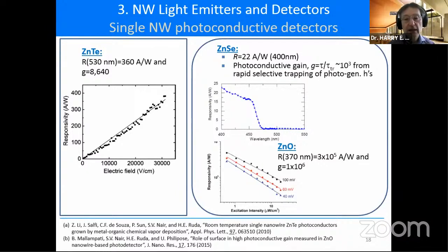So here's a bunch of examples for you of work we've done on making photodetectors, photoconductive detectors, and what you can see is, unlike normal traditional detectors where we're talking about amps per watt as a normal number, if we look, for example, at the zinc oxide one at the bottom there, you can see that we can have numbers like millions of amps per watt from or close from these wires, and that's because the gain is very high. And what's happening, and we're going to come back to that, is charges get selectively trapped in these structures, which means that the lifetime of the other charge is essentially indefinite, and we get very high gain as these secondary charges are circulating effectively indefinitely around the circuit.